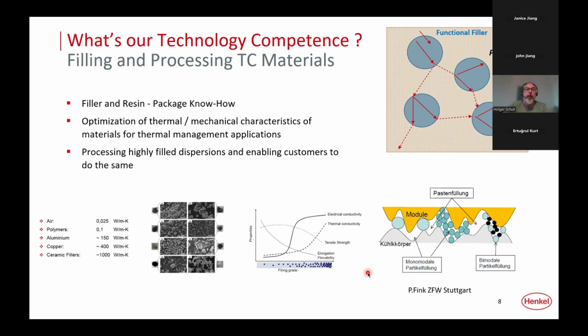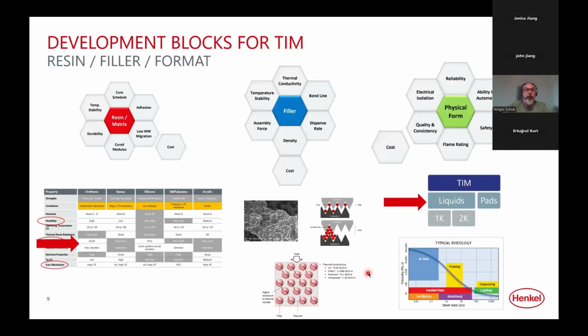So when we develop those thermal interface materials, as mentioned, we are looking at the resin, what we call the matrix. So that's the base material. We either could use polyurethanes, epoxies, silicone material, silane modified polymers, or even acrylic material. And depending on the key requirements, if it needs to be super elastic or chemically robust, we pick those kinds of raw material, and then considering all the requirements and effects you can have from the resins, we use different types of fillers which are relevant for thermal conductivity, for the achievable bond line, so how thin you can press the material, but also the dispense rate.